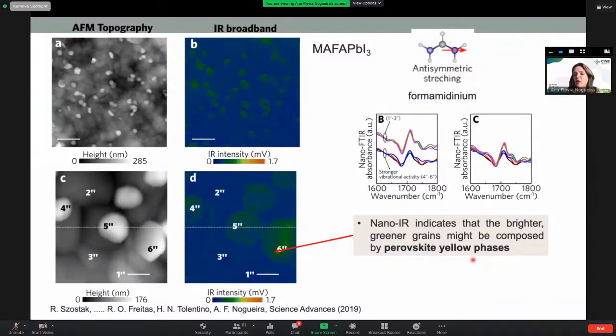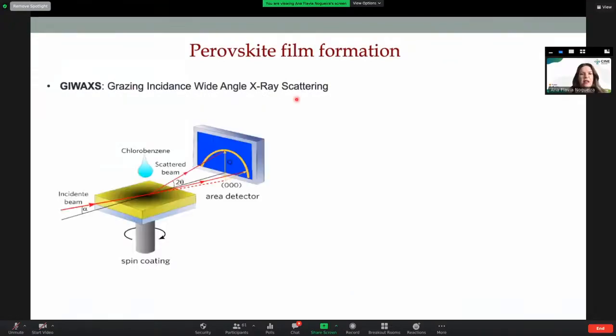Of course, in this work we used other techniques also to prove that. But what was interesting is that we could map the morphology and the composition using this technique that, as I mentioned, is going to be available next year here at Sirius. But when you go to the perovskite film formation, we went back to the synchrotron and used what we call GIWAXS, grazing incidence wide angle X-ray scattering. So basically, this is the result that you have.